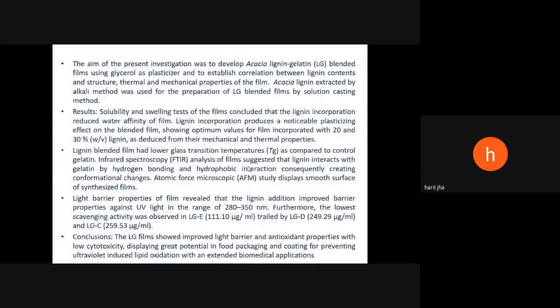In this work, the aim was to develop an acacia lignin and gelatin blended film using glycerol as plasticizer, and to establish correlation between lignin contents and structure, thermal and mechanical property of the film. Acacia lignin extracted by the alkali method was used for the preparation of lignin gelatin blended films by solution casting method. And the results of solubility and swelling tests of the films concluded that lignin incorporation reduced water affinity of the film, and lignin incorporation produces a noticeable plasticizing effect on the blended film, showing optimum values for the films incorporated with 20 and 30% weight by volume lignin, as deduced from their mechanical and thermal property.